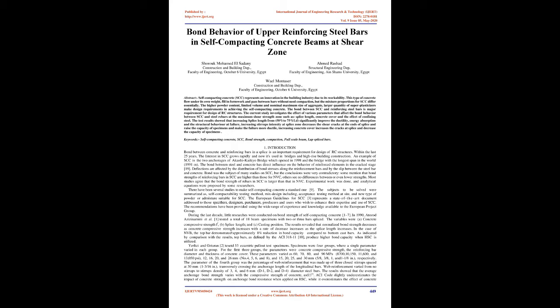Increasing stirrups intensity at splice zone decreases the shear cracks at the ends of splice and raises the capacity of specimens and makes the failure more ductile. Increasing concrete cover increases the cracks at splice and decreases the capacity of specimens. Keywords: self-compacting concrete, SCC, bond strength, compaction, full-scale beam, lap-spliced bars.